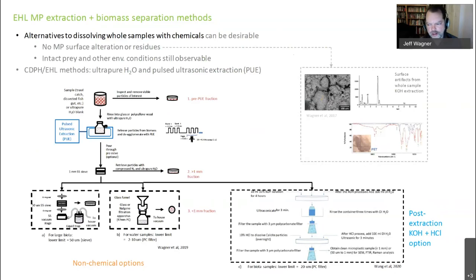For one, on the upper right, you see some SEM images, FTIR, and we also took Raman data from the study that showed that we were getting some surface contamination through the whole sample dissolution process. In this case, potassium salts, which you see in the upper right. We wanted to avoid that, and there have been plenty of publications that have shown ways of avoiding that. But in our case, it's also desirable to avoid dissolving the whole sample because we are interested in looking at intact prey and other environmental conditions of the samples before destroying them.